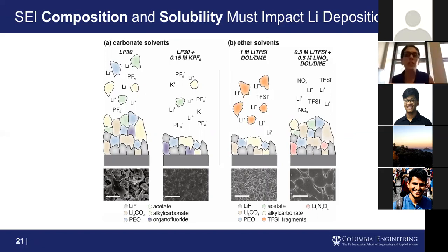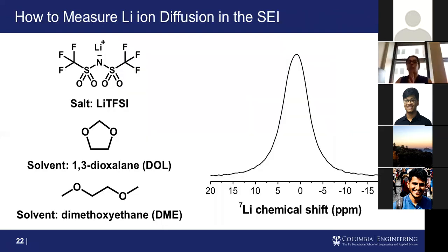So we were very intrigued by this idea and we wanted to test this hypothesis. So we had to come up with a way to actually measure lithium ion diffusion through this layer and compare it to the case with just the TFSI. Like I told you in the beginning, the very beautiful thing about NMR is that you can measure both structure and dynamics. So here we're interested in measuring the dynamics of the lithium ions.